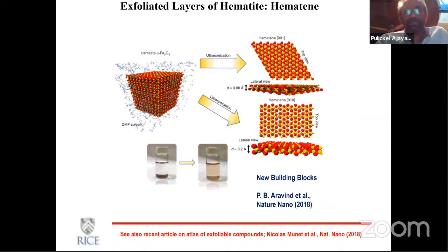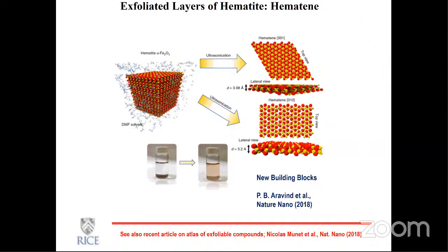Of course, in a layered system, it's much easier to see that things would cleave along the basal planes. But even systems that are not traditionally layered, like in this particular case, you're seeing an example of iron oxide, one could cleave along certain directions if the conditions are right. And then you can explore the properties of these super thin layers. And the hematite, or alpha iron oxide, which is not truly magnetic, appears to have some magnetic properties when you go to very, very thin levels.